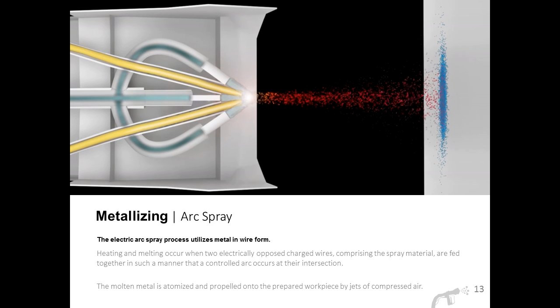In the bridge industry, arc spray is the most common form of applying metallizing. And what you're seeing here above is just a static depiction of what the internal workings of an arc spray application gun look like. Through arc spray, two electrically opposed wires, which you see in yellow, are fed through the gun, similar to what you'd find in a welding machine. Because of their strong opposing charges, an electric arc forms at the intersection. The heat from the arc melts the wire, and the molten metal, either zinc or aluminum or a mixture of the two, is propelled onto the steel girder by jets of compressed air.